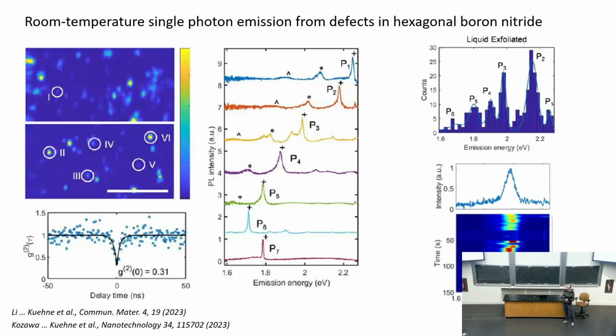NV type centers in diamond have been the inspiration here. So people say, oh, it's like a nitrogen vacancy, or it's like a nitrogen vacancy plus a carbon substitution. And so there's all sorts of thinking about how this looks at the atomic scale. But the fact is you see very many different energies. Here in our work, we suggest that there's even grouping in this specific window of emission energies. And they have interesting features, like they blink. You can make them more stable. So here we have a blinking emitter. And if you encapsulate it very well, you can make it more stable.